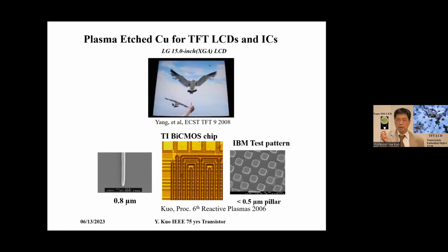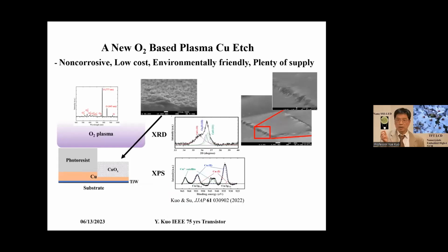So copper lines actually can be etched with chlorine plasma at room temperature using a conventional parallel plate reactor. And every company has a facility, every company has equipment. The reason people cannot solve problems is that they are thinking the wrong way. And further on, our recent work shows oxygen can even replace chlorine, because chlorine is corrosive, undesirable. So if we use oxygen, we can do the same reaction, convert the copper to copper oxide, then strip with HCl, to form copper lines. So that's a further improvement, making it more user-friendly for production, because oxygen has plenty of supply at low cost and is environmentally friendly.